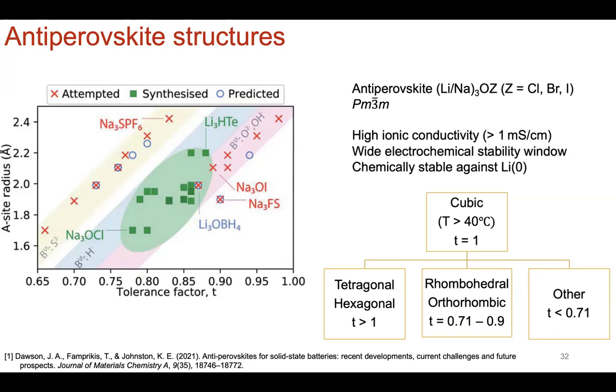You're going to have an issue with manufacturing of these compounds and controlling their electrochemical performance within a tight temperature range. Because even at 40 C, right, we're talking about anything close to that, like 30 C, which on a very hot day with enough humidity, you can induce certain phase transformations more readily. So the temperature window is going to be an issue because you want the high temperature phase, and that's great, but the phase transformations to tetragonal, hexagonal, rhombohedral, all of these crystal structures can occur.